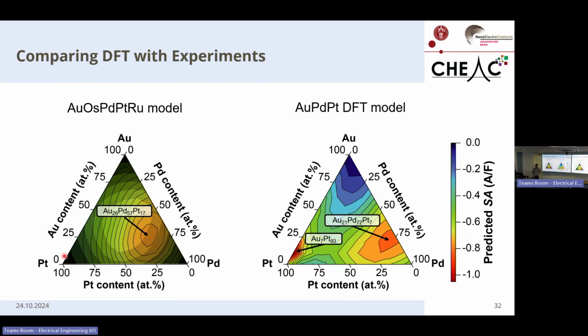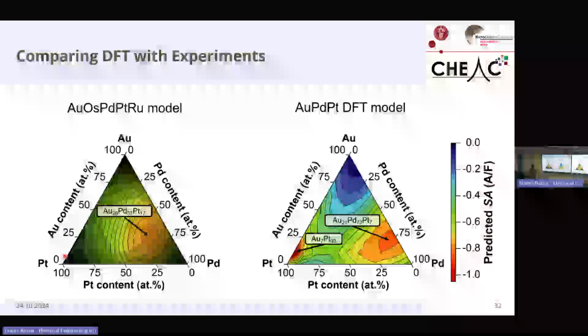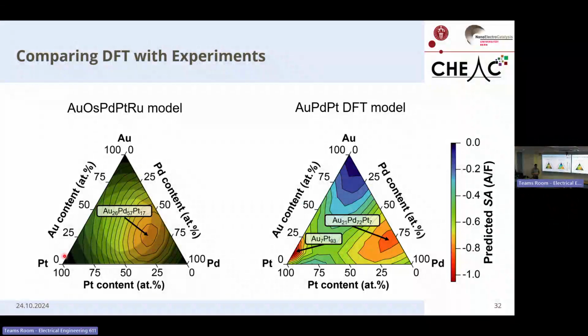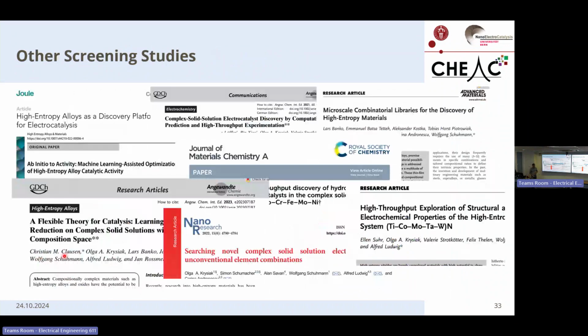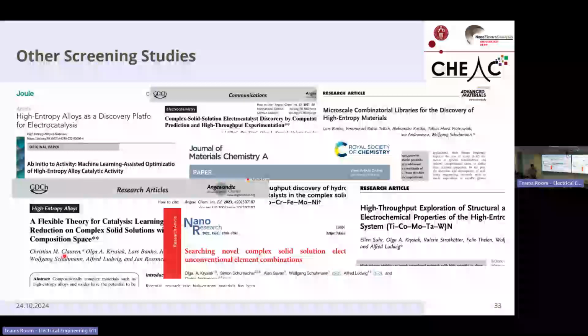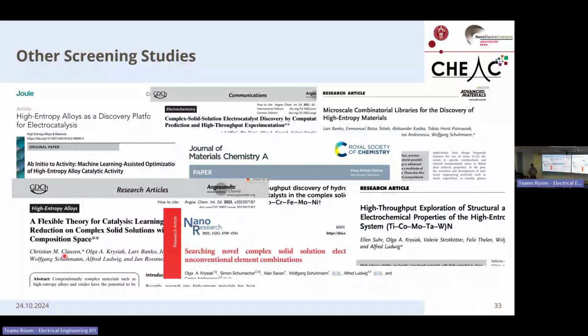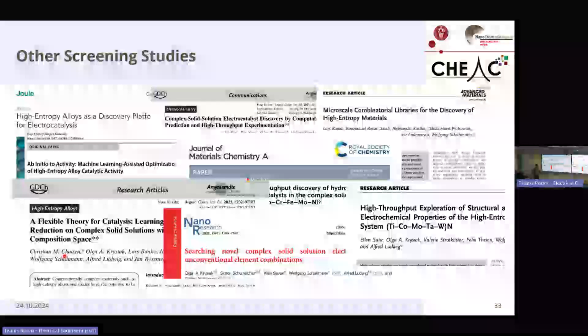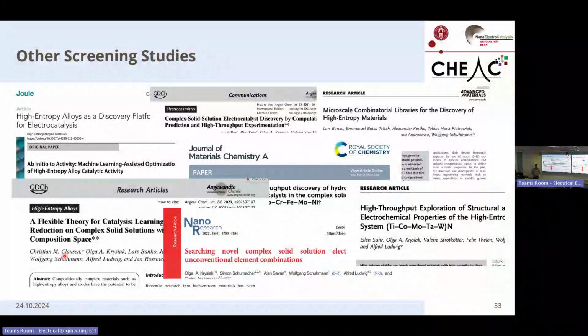So eventually, we started with 8 elements, we funneled it down to a 5-element space, funneling it down to a 3-element space, and it turns out that the most active catalyst for the oxygen reduction is still the pure platinum catalyst. And I would say this is not the first study that ended up in a disappointment, because if you look into literature, you will find other screening studies, and most of them end up also with the same conclusion that the most active catalyst is a binary, or in some cases, a ternary alloy.